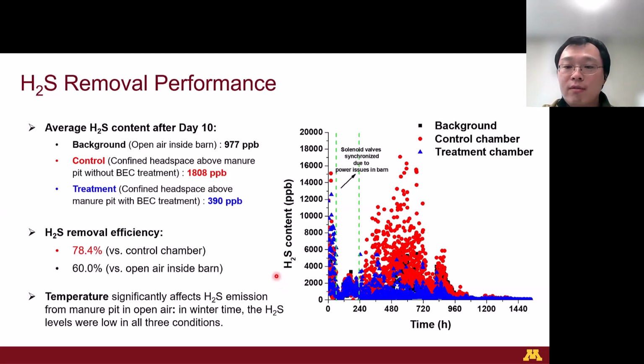The hydrogen sulfide level drop in the BEC treatment chamber headspace corresponds to an almost 80% reduction compared to the control chamber without the electrodes. And it also shows a 60% reduction compared to the open air inside the barn. These results confirm that our BEC treatment effectively mitigates hydrogen sulfide emissions at scale.